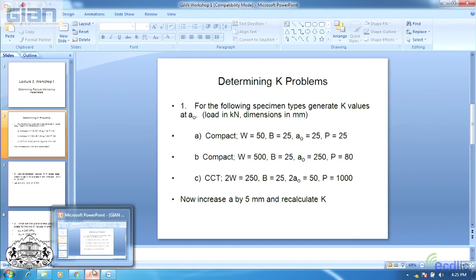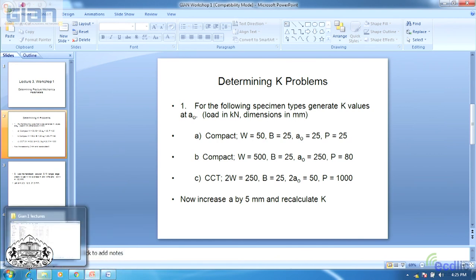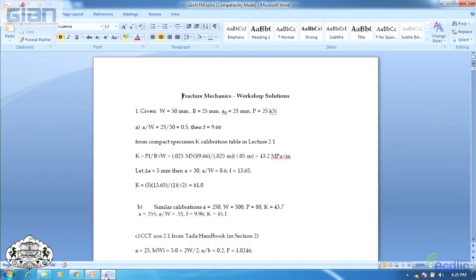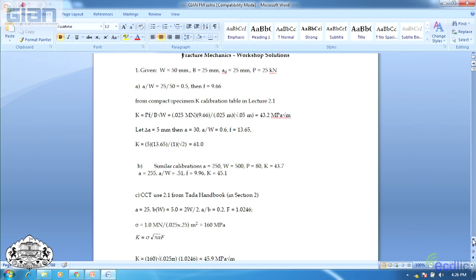The center crack geometry: 2W or 2B is 250, thickness is 25, 2A is 50, and load is 1000. These are all millimeters and kilonewtons. The K solution, you should definitely use that picture. So I have here A is 25. B or W is 125, which is 2W over 2. A over B is 0.2. Then if you read from the table and don't use the graph, F is 1.0246.